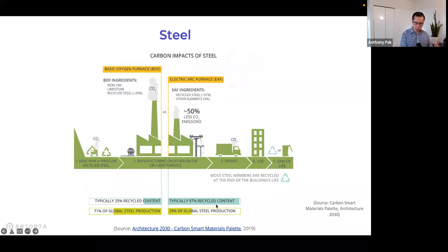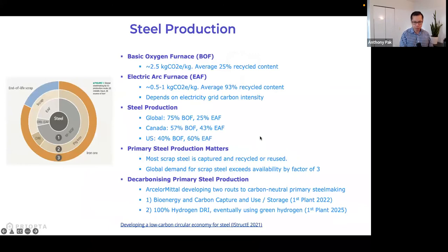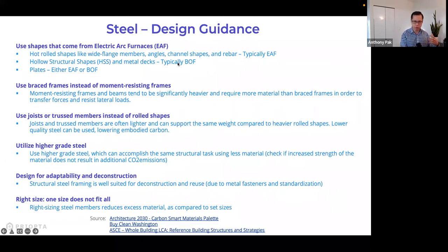With electric arc furnace, you're using mostly recycled steel. So that accounts for maybe just under 30% of global steel production. And it's, as I mentioned, much lower emission intensity. And because it's an electric driven process, it matters what the carbon intensity of the electricity grid is where that steel is produced. So generally speaking, I think in Canada, we're about 57% basic oxygen furnace, that's the higher emission variety, and about 43% electric arc furnace. And so on a project level, if you can specify electric arc furnace steel from lower carbon states or provinces that are producing this, that can generally reduce the carbon intensity of your project.